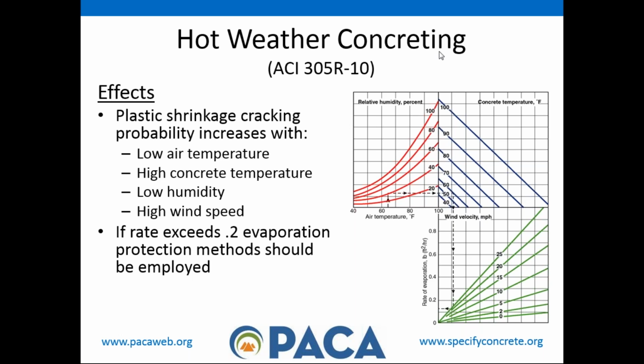This is a really nice graph used to determine probability of plastic shrinkage cracking. Everybody remembers, I'll just use my mouse. I'm not going to draw like Jim did, but you can just follow. If you have the humidity to the concrete temperature down to the wind velocity, and it's greater than 0.2, you're going to have problems. And if you don't have an evaporation retarder that Susan mentioned, like a Confilm or Evapora, you're going to have an issue. You're going to have plastic shrinkage cracking.